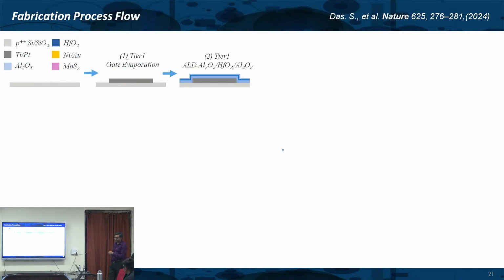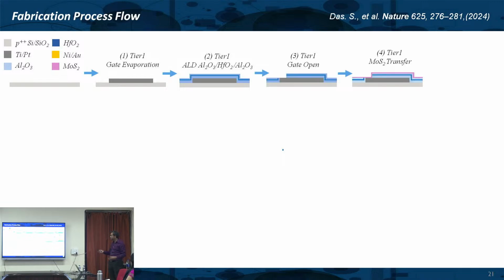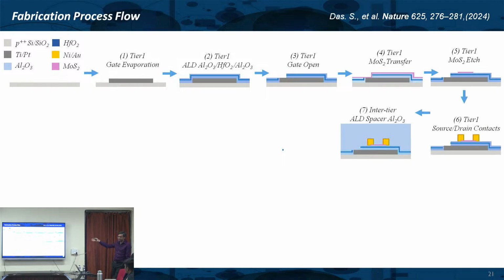Then we transfer the MoS2. Then we again pattern using e-beam, right? And then we etch the MoS2, right? Now I have a channel, I have a dielectric, I have a metal electrode. Then I do another e-beam lithography and e-beam evaporation to put the source and drain contacts, right? This is how we make tier 1. After that, you put the inter-tier dielectric, because we have to isolate them electrically, right? So we put something like an aluminum oxide spacer, it's an insulator. So that is my full fabrication of tier 1.